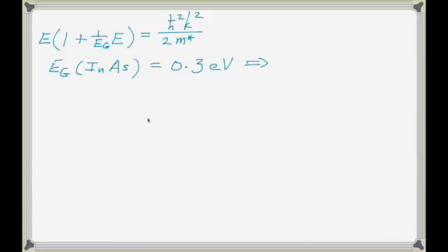So you're 1 over the band gap. It's like 3 1/3. And this gives you an idea how large your energy is before this term starts to become important. As your energy starts to increase to some fraction of the band gap, then this starts to look more and more parabolic. You start diverging from your parabolic dispersion.